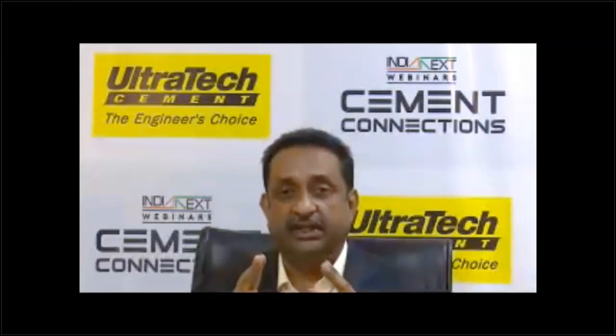Kindly guide, this is Shantanu Pandey, kindly guide on the possibility of using C&D waste in concrete. It's a very good question. C&D waste aggregates are permitted, both sand and 10 mm and 20 mm aggregates, in the latest revision of 383. In structural concrete up to M25, you are allowed to use 20%, 25% of either sand or aggregates. But then sufficient precaution has got to be